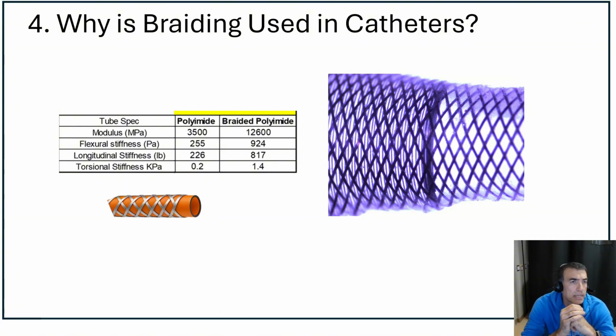Why is braiding used in catheters? Braiding is a metal wire structure that is used in catheters, and the main function of braiding is that it improves the tensile modulus of the structure. For this example, you can see that the polyimide material, when it is braided, the modulus would increase significantly, almost 4 times. And that increase in modulus would increase the flexural stiffness, the pushability, and torqueability.